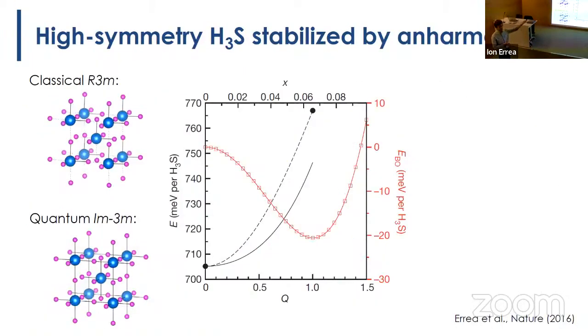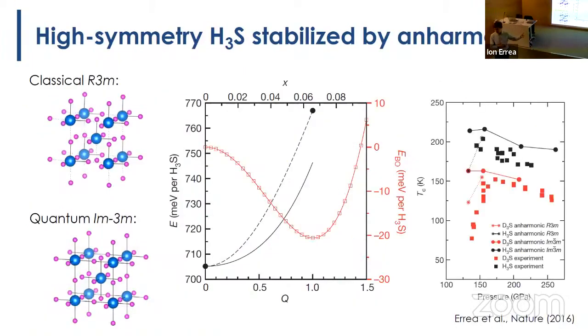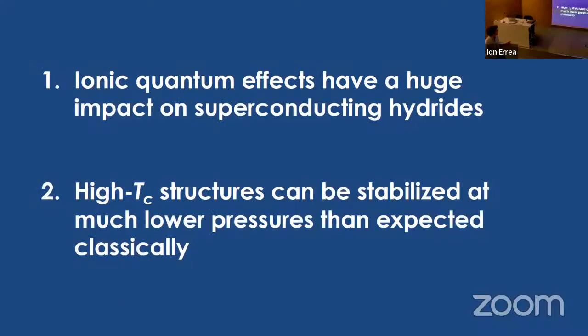This is H3S. Similar things we have seen in different compounds as well. So this is the message that I want to give here: ionic quantum effects have a huge impact on superconducting hydrides, and high Tc structures can be stabilized at much lower pressures than expected classically. So if we want to find high Tc compounds in these families, we really need to consider these effects, because they will make stable structures at much lower pressures than predicted classically. I think it's very important to consider this.